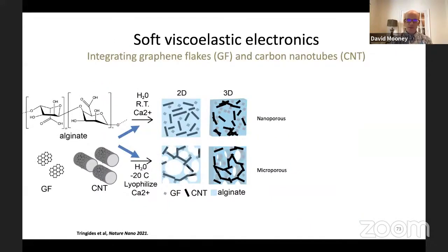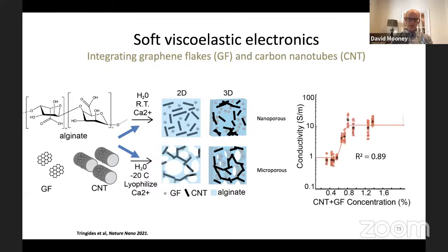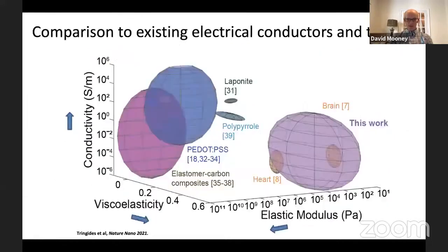As I mentioned, we want to make the electronics component soft as well and viscoelastic. So we're utilizing graphene flakes and carbon nanotubes to accomplish this, and to minimize the quantity of these materials, which could otherwise dramatically stiffen the gels. We use a technique to create microporous materials to concentrate the particles just in a fraction of the entire volume. And this allows us to get percolation, electrical passage, at very, very low solids content, where we don't have any significant impact on the bulk mechanical properties of the layers.